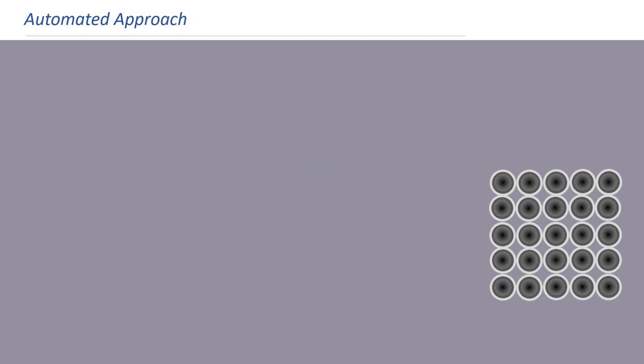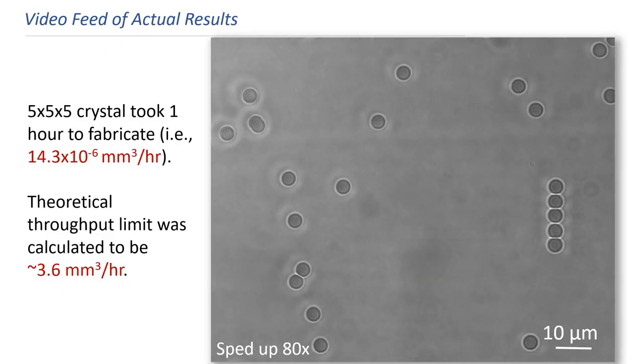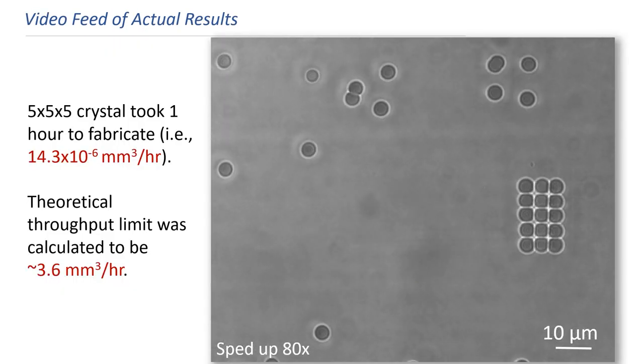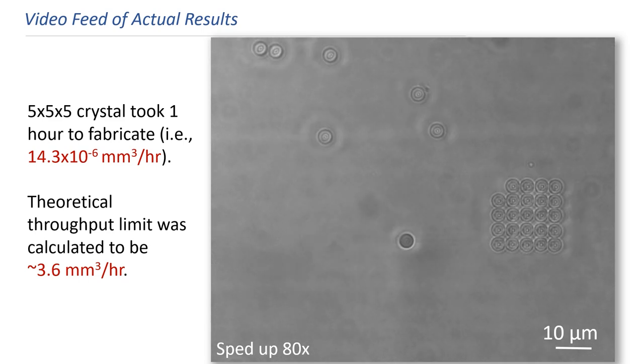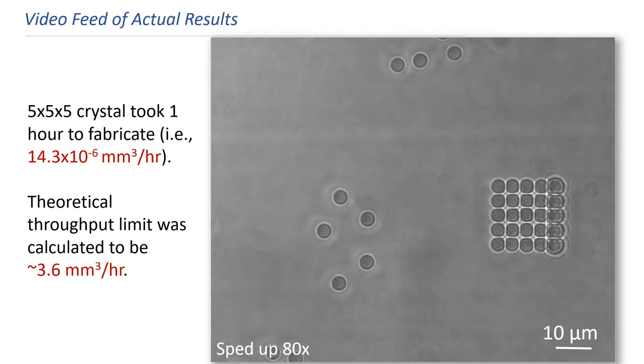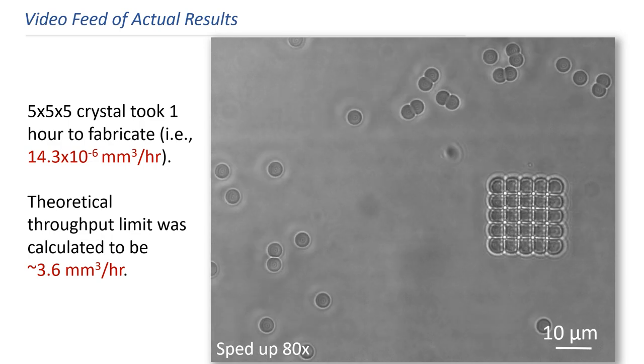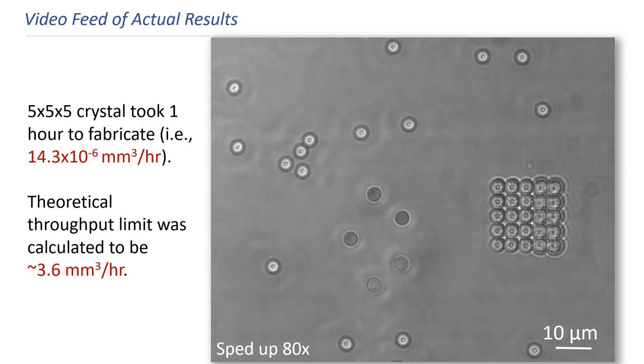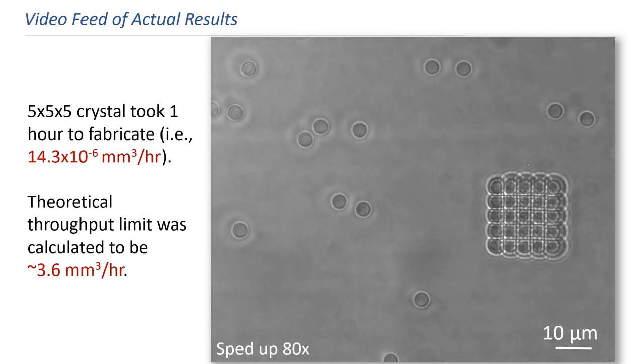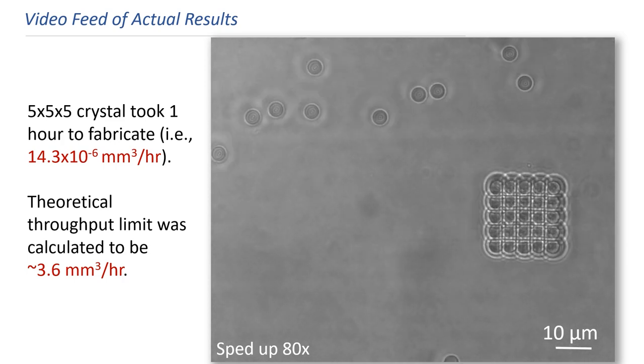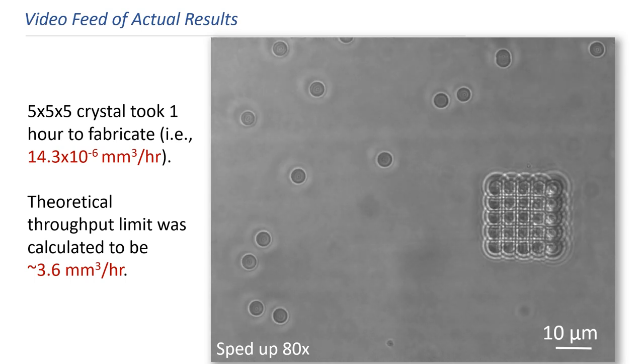Note that although this crystal shows a cubic packing configuration, users of the automated system can upload any combination of sphere locations and then the system will automatically assemble the crystal as desired without further operator input. This is an actual video of the entire approach in action as it autonomously assembles a 5x5x5 crystal. The video is sped up 80-fold, but the system's calculated throughput is 14.3 times 10 to the negative 6 millimeters cubed of crystal printed per hour which although is orders of magnitude faster than other manual optical tweezer assembly approaches is still underwhelmingly small.